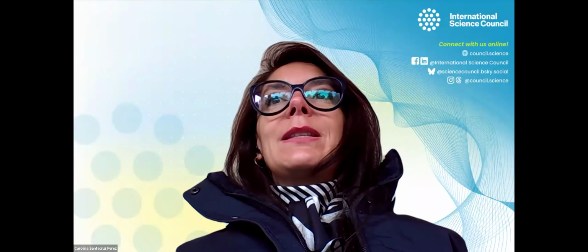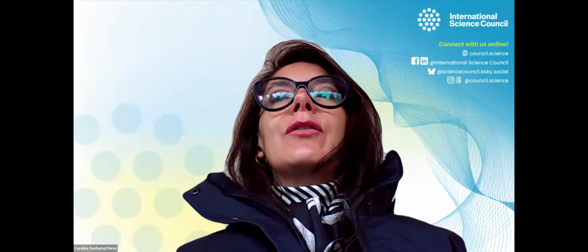Let me start with Patrice, saying, please, could you give us details about the precipitation of graphene in the sample? I can tell you a little bit, because it's not my scientific case. In fact, it belongs to another researcher who works with me. If you want much more details, you can send me a message and I'll forward it to Flavia. But as far as I know, her student prepared this. It's a very common ceramic composition that's a mixture of yttria, alumina, and it has zirconia too. And he could prove that by putting graphene, the hardness increased in the ceramic, which is not something that I would say without proving that.